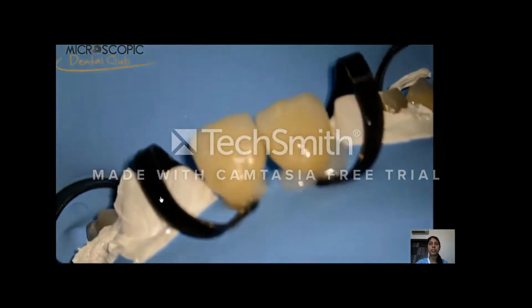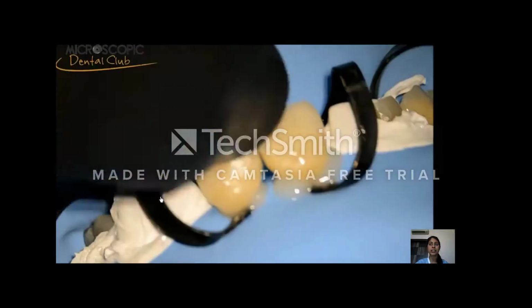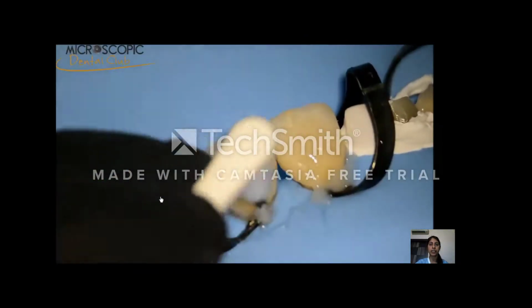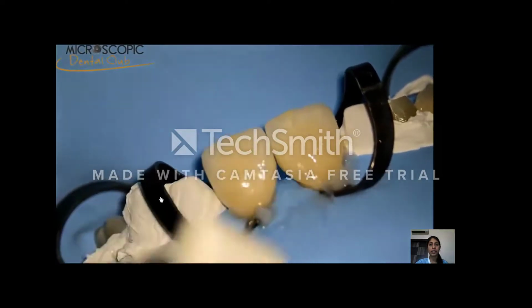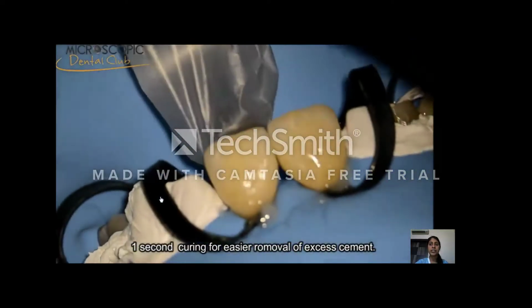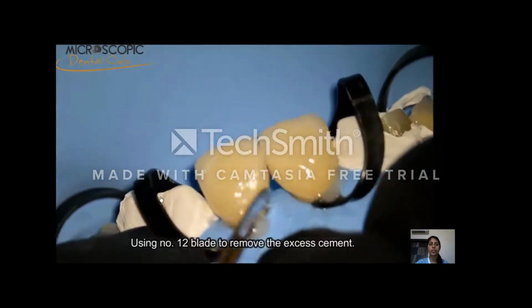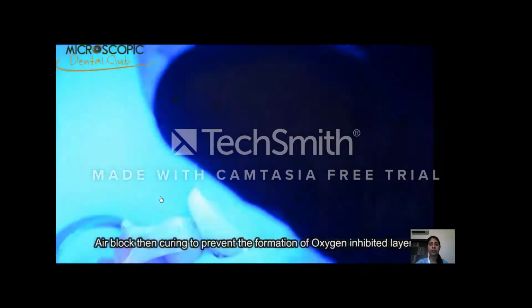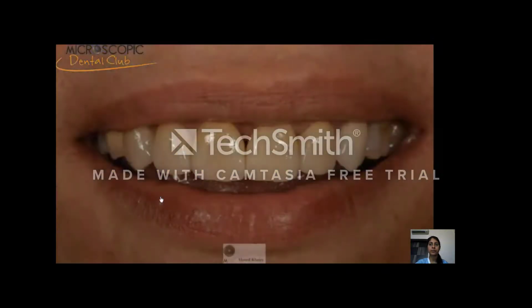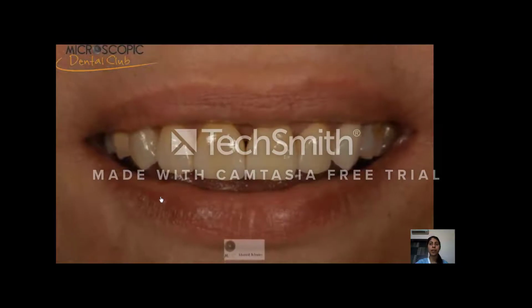Etching of the internal surface of veneers is also done with 10% hydrofluoric acid for 20 seconds, followed by application of bonding agent containing silane coupling agent and is light cured. Resin cement is then used to cement the veneers. The excess cement is then removed. Flash curing is done for 1 second for ease of removal of excess material with help of a BP blade, followed by complete curing. This is the post-operative view after finishing and polishing.